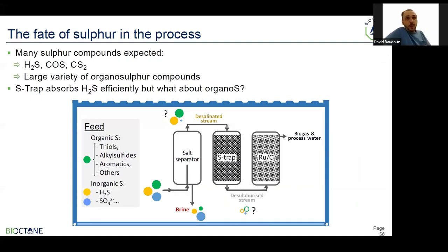Of course there are some simple ones, H2S being the most obvious one, but also COS, CS2, and of course a lot of organosulfur compounds, a very broad variety of them. And our process has to deal with all of them. And of course there are sulfates present. The salt separator will allow removing most of the sulfate, and some other organosulfur compounds that are charged or ionic, but there's still a big amount of them that can reach the sulfur trap. And in order to optimize the trap and its catalytic compound, we need to first identify them in order to better convert them and trap the sulfur.